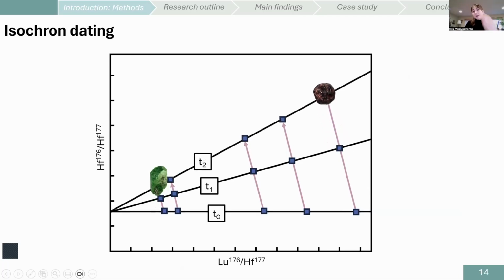We go to T2, that's our final time, that's when we collect the sample, grind it, dissolve it, and try to extract the Hf. What we have here is this slope of the isochron telling us exactly the time where the accumulation started. To build this kind of robust isochron, as you've seen, we need something to anchor it at the low parent-daughter ratio and at the high parent-daughter ratio. With the garnet-bearing samples, high parent-daughter ratio is easy. It's usually going to be garnet. And at the low end of the isochron, we're either going to have clinopyroxene data, or if we don't have clinopyroxene in the mineral assemblage, we can use the whole rock data, which is also going to plot at the low parent-daughter ratio of the isochron.